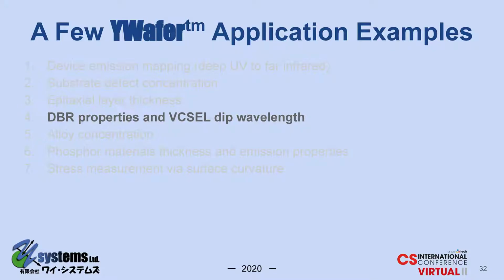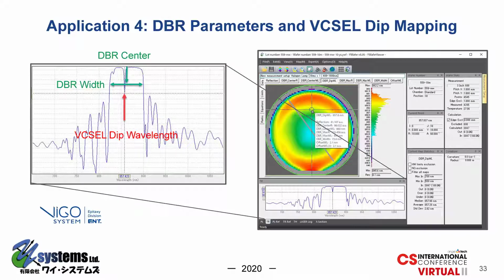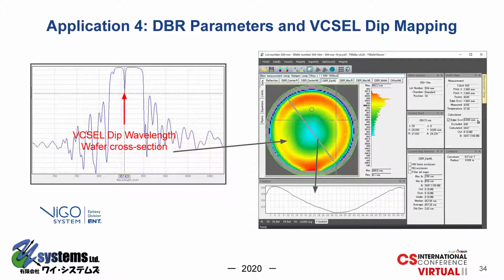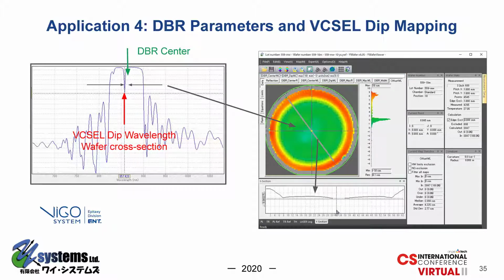Moving on to more device-related applications, combining photoluminescence and reflectivity for VCSEL structure analysis is now, of course, a standard process. The YWafer spectral analysis allows mapping of just about any feature of a DBR layer, including mapping of the dip wavelength from the underlying cavity structure. Plotting the wafer cross-section of the dip wavelength, or even generating a map of the difference in wavelength between the DBR center and the dip wavelength is trivial using our standard mapping software.